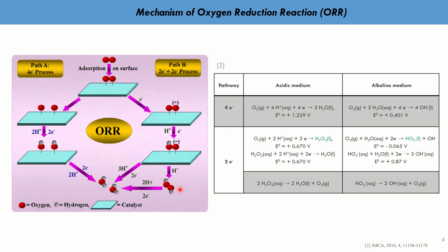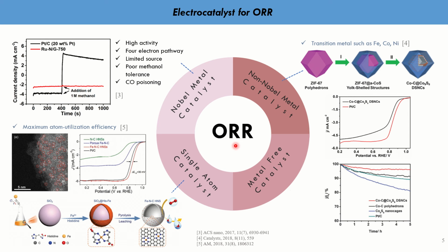In general, oxygen reduction reaction would take place principally through 2 different pathways, including the 4-electron pathway and the 2-electron pathway. ORR electrocatalysts can be divided into 4 categories: noble metal, non-noble metal, single atom, and metal-free electrocatalysts. Although platinum-based electrocatalysts have been renowned for their great ORR activity, the poor carbon monoxide and methanol tolerance has limited their development.